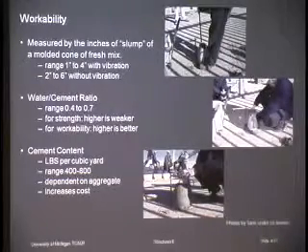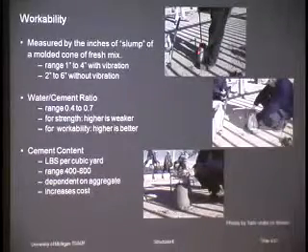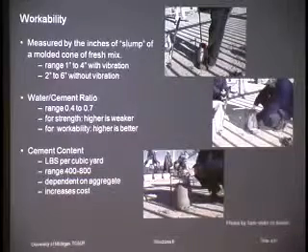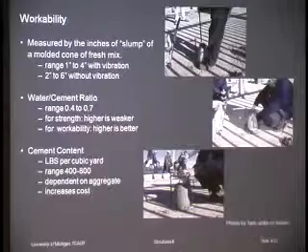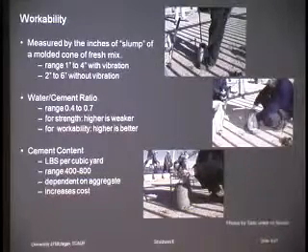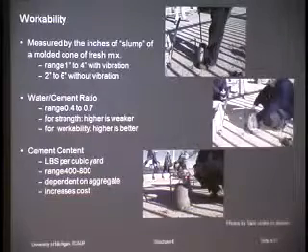The way this works is you simply cast this cone of concrete, and then you lift it up. It's an ASTM procedure. You put the cone down, you pour in a third of the cone, 25 rods, another third, 25 rods, another third, 25 rods, lift it off, set the cone beside it, like he did. Well, he didn't. He has a special thing. Usually, they set the cone beside it.